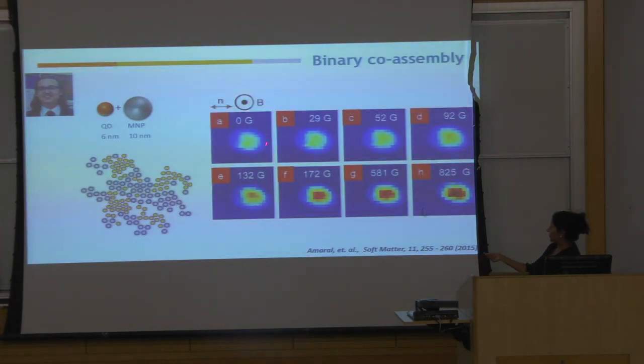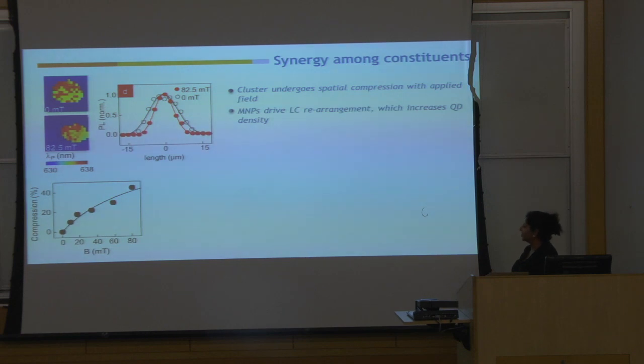We are imaging the emission intensity of these clusters. The magnetic nanoparticles don't emit any light. The quantum dots do. So we're looking at the emission from the quantum dots. And as we apply a very small field, the emission intensity from the quantum dots increases several-fold. So we have a mixture of quantum dots and nanoparticles. We apply a magnetic field, and the quantum dots start emitting brighter, which was a weird, unexpected observation. The other thing we looked at here, we are plotting the wavelength, the color that it's emitting.